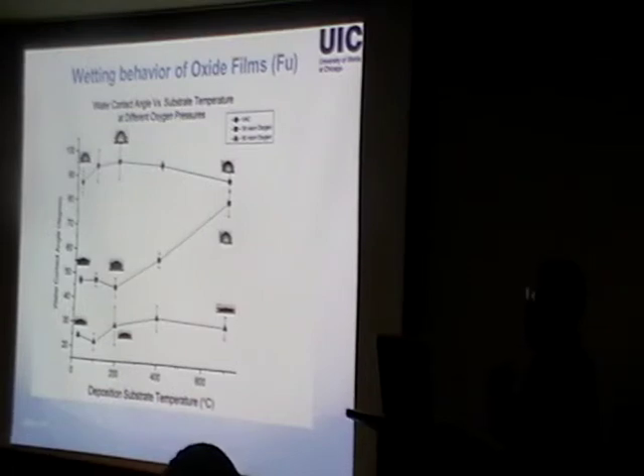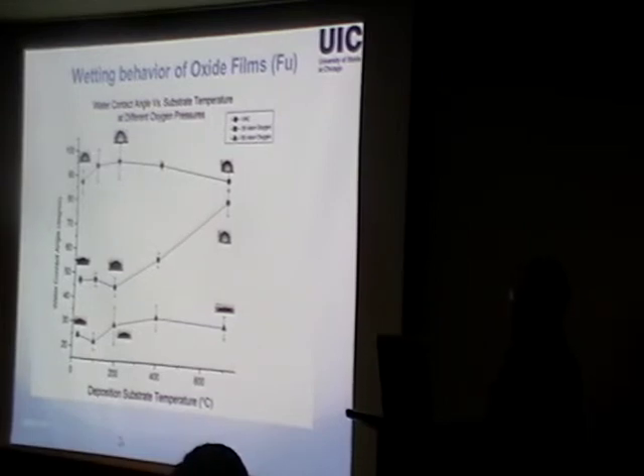Okay, so the way we make the sample is you put the substrate in, you turn on the vacuum pump until the pressure gets really, really low, right? And that allows us to make a very, very clean sample. So basically what we see plotted here is the water contact angle versus the deposition temperature at different oxygen pressures. What you see is that 50 millitorr, this bottom curve, is pretty much flat. The contact angle is fairly low, and you can see the pictures here on the inset. Contact angle is between 20 and 30 degrees. So this is a hydrophilic type of surface that you will see for a typical oxide material.